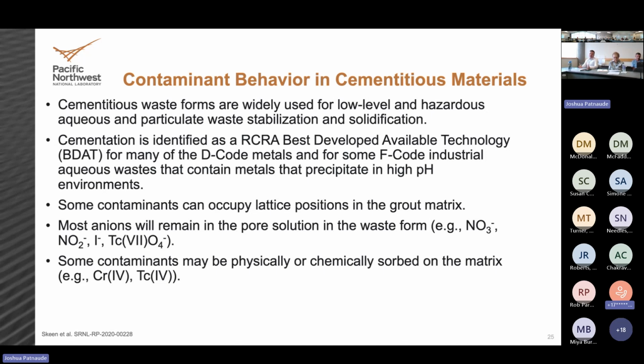If we're doing liquid waste immobilization, what happens when we mix our dry reagents and that liquid together? So that liquid contains this range of chemical components, contaminants, and in some cases radionuclides in there. As the dry reagents start reacting, the water starts to get consumed. Where the pores come from in cement is spaces where there used to be water. It is a way to think about it. There's a decent correlation between your resulting porosity and how much water you started with.